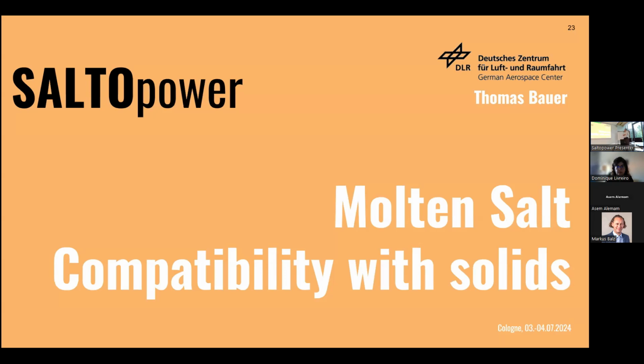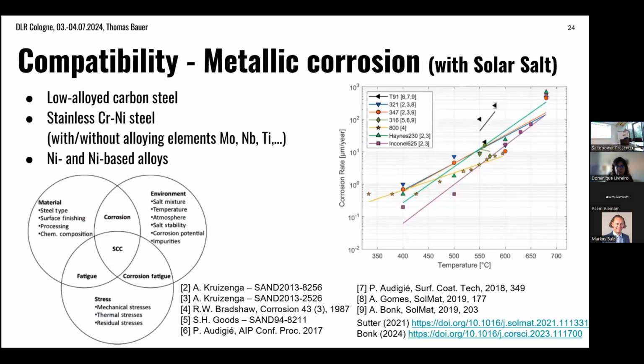Then some words about the compatibility with solids. So of course, there are metals, and we need to look at the corrosion. I only show here the corrosion with solar salt. For solar salt, we work with different alloys. We can work with low alloyed carbon steel up to 400, 450, maybe 480 degrees. Then there are some chromium alloys, and then stainless steel is the main alloy at up to 560 degrees. There are different types with different stabilizing elements like molybdenum, niobium, or titanium. Typically also there are carbon enriched at the high temperatures.